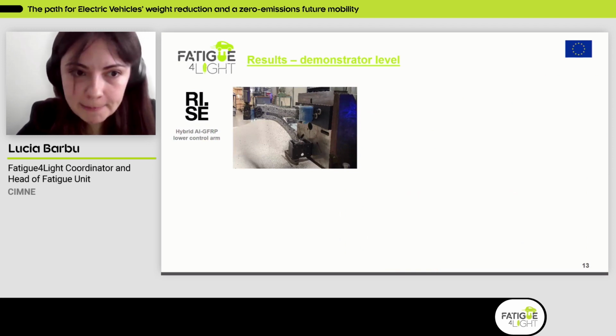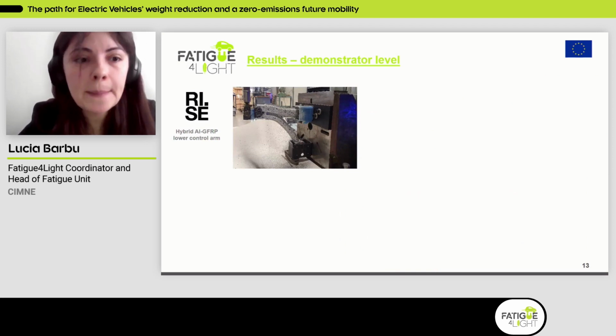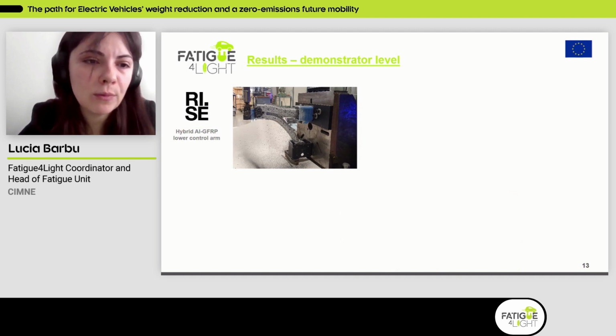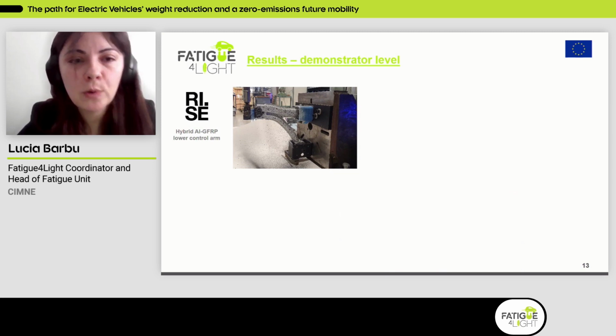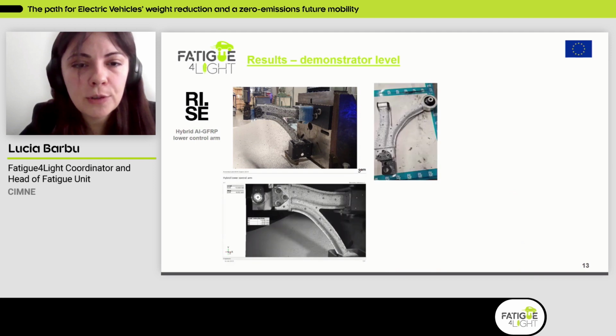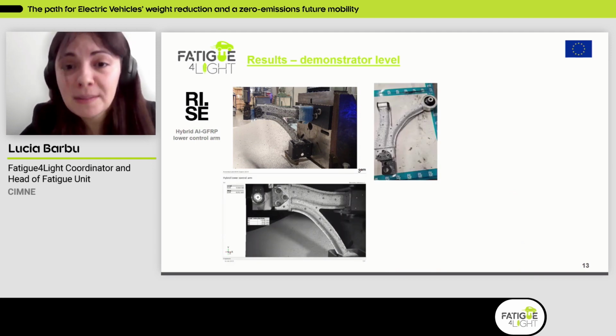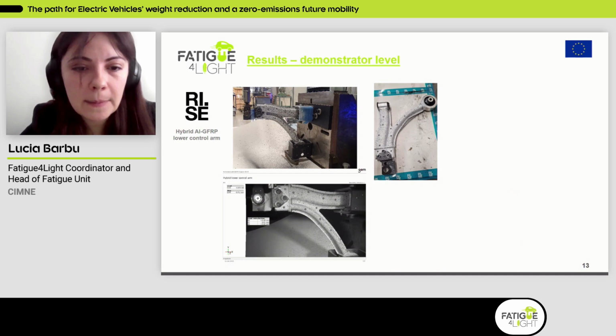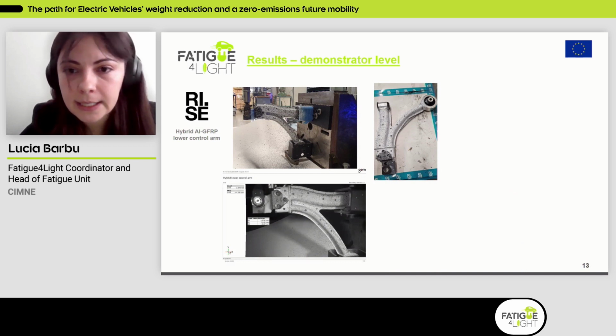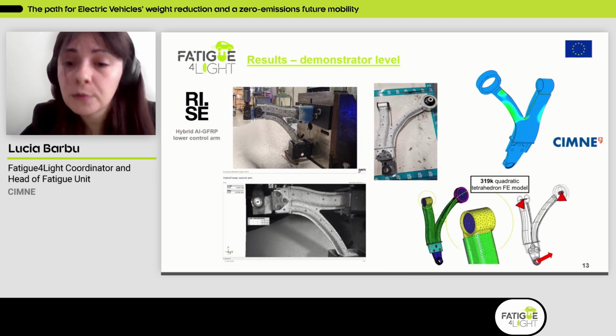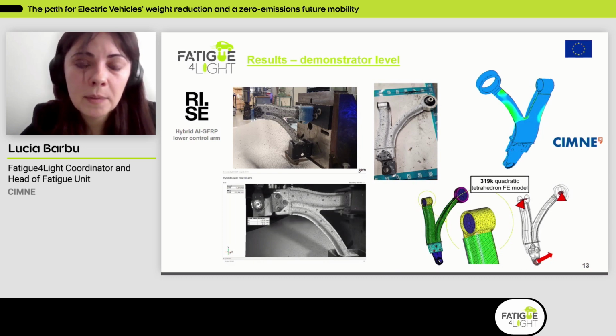So our colleagues at RISE Research Institute of Sweden built, tested, and analyzed this hybrid aluminum GFRP lower control arm. You can see here an image of the component which is screwed to the test bench. And afterwards, an image of the failed component, and also just a short animation of a digital image correlation test. Okay, from the numerical perspective, of course, we built models for this, we analyzed it, and later on you will see the performance that we got from the numerical point of view.